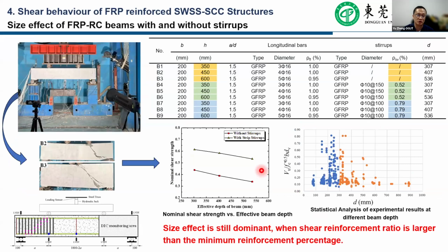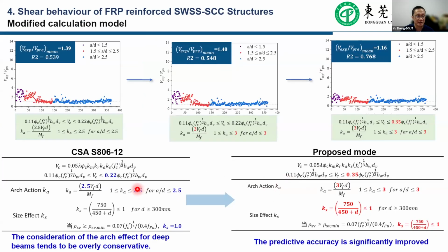And furthermore, we also developed a study of the size effect inside the concrete beam. These are our test results. We can find that the size effect is still very dominant, very dominant in the FRP reinforced seawater and self-compacting concrete. Based on those two observations in the test and the analysis, we can try to modify the CSA model.